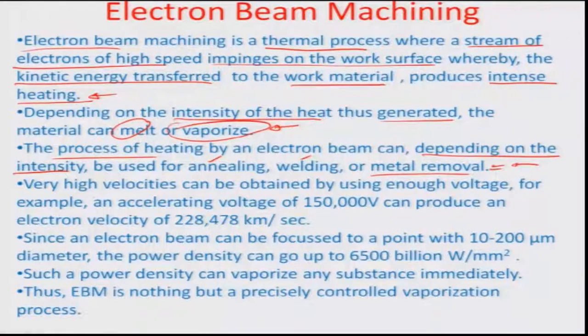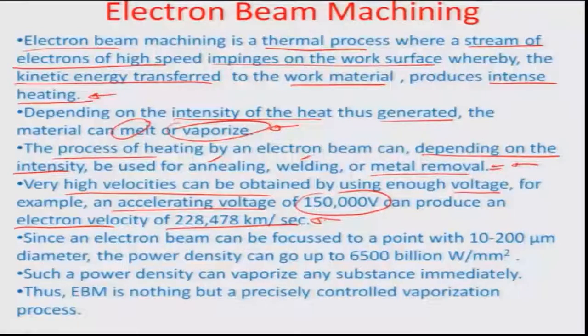So very high velocities can be obtained if you use higher voltages. For example, an accelerating voltage for the electron beam of about 150 kV would produce electron velocities which are almost near the speed of light, about 228,478 kilometers per second. Since an electron beam can be focused to a point by magnetic fields almost as narrow as 10 to 200 micrometers, and in fact this limit has gone down further these days, the power density of that particular point can go up almost to the level of about 6500 billion watts per millimeter square. So such a power density obviously can vaporize any substance which comes in contact with it immediately.